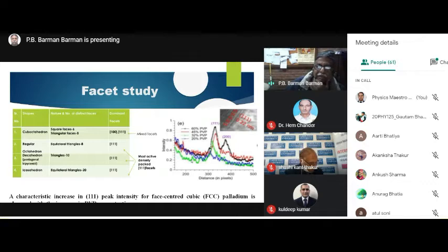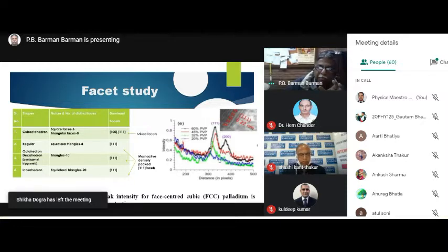We have done the XRD and compared it, and you can see that at 32% PVP the 111 surface is the dominant facet in all of this. In case of regular octahedron, we have seen that the 111 facet plays an important role, and as we saw earlier in the XRD, this facet shows high intensity, and this facet is responsible for sensing the hydrogen.